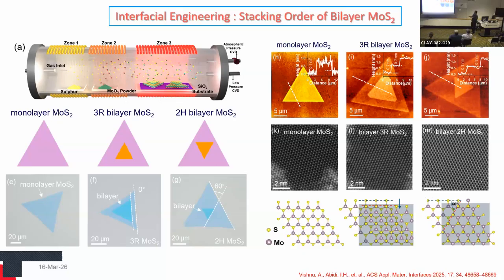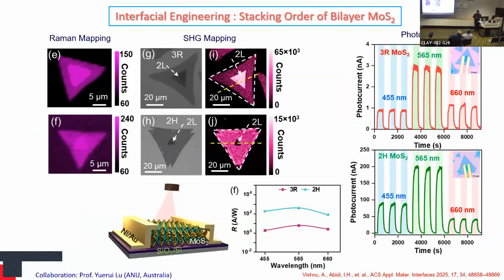So we can control with the conditions. You can grow different stackings of the bilayer MoS2, and they have different properties once you have 2 different types of bilayer MoS2, for example, 2H and 3R. In our case, 2H gives us higher photo response as compared to the 3R, which is because of the interlayer coupling between the 2 layers. Once you have a 2H phase of bilayer MoS2, we have higher interlayer coupling, which actually enhances the overall response in the optoelectronic properties.